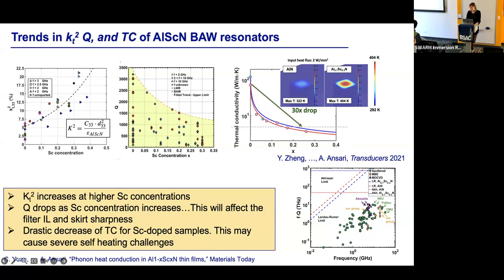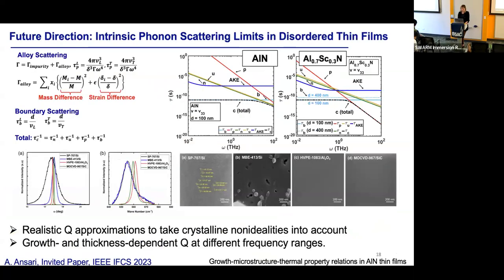Another thing that we have been looking into is the intrinsic phonon-phonon losses in aluminum nitride and aluminum scandium nitride materials. If you take a look at the Akhiezer and the Landau-Rumer limits, which are intrinsic phonon-phonon losses in these material systems, you will see that all the reported data is a lot lower than what the theory suggests, right? So we're interested in looking at the fundamental limits in disordered thin films, especially when the film gets thinner and thinner. A lot of factors play a role in adding more scattering losses in acoustic materials and devices.